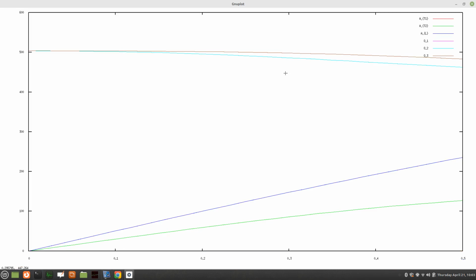Okay, now you can see. Although, I will increase the line width next time. The lowest green line is actually 2 modes, acoustic transverse. There are 2 modes and they are overlapped. I showed you in the data also, they are the same. And the blue line is the acoustic longitudinal mode. It has higher frequency. You can also notice that. I told you that will happen. And the other 3 branches on the top are the optical branches. The lower 2 are optical transverse, and the last one is optical longitudinal. So this is how we got 6 branches in the silicon crystal.